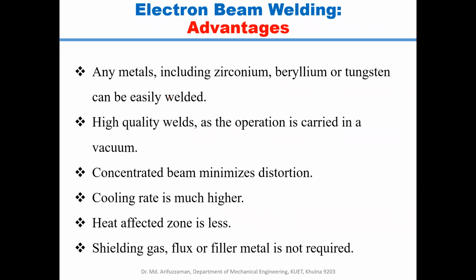Any metal, including zirconium, beryllium, and tungsten, can be easily welded. It gives a high quality weld, and the operation is carried out in vacuum, so there will be no weld contamination or impurities. A concentrated beam minimizes the distortion. That means since the welding zone is very small, bending or any kind of distortion of the specimen does not occur. The cooling rate is much higher compared to other processes. The heat affected zone is small, and shielding gas, flux, and filler metals are not required in this case.